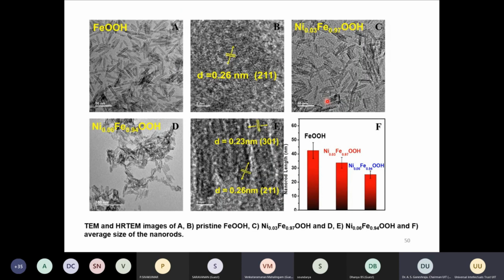These are the TEM images of this material. You can see that they are nanorod morphology and they are crystalline as well, which we can find out from the d-value, which corresponds to the 211 plane. And this is for the nickel iron oxyhydroxide. We tried to reduce the nickel further, but 6% we found gave the optimized results. And this is the aspect ratio, the nanorod length is plotted, where we have longer rods,